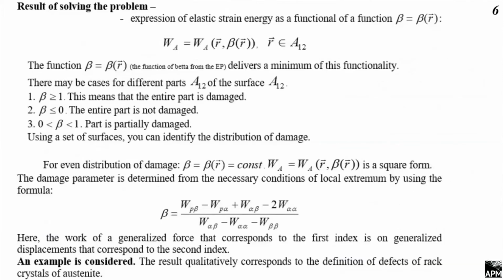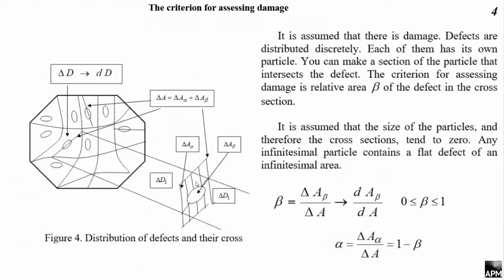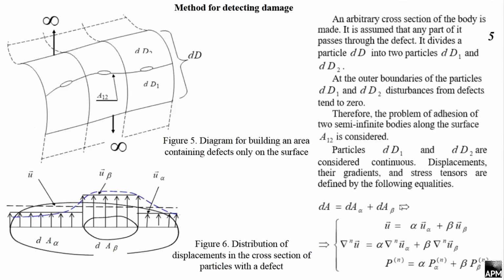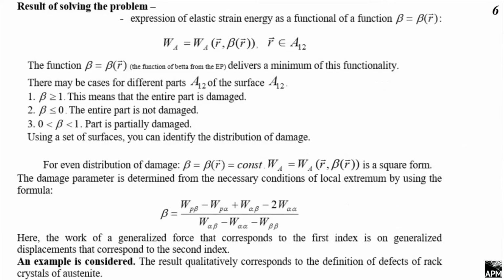Therefore, the problem of adhesion of two semi-infinite bodies along the surface A12 is considered. Particles DD1 and DD2 are considered continuous. Displacement gradients with stress tensors are defined by the following equation. Result of solving the problem: expression of elastic strain energy as a functional of a function beta. Beta is a function of r. Potential energy is a function of R and beta. The function beta delivers a minimum of this functional.